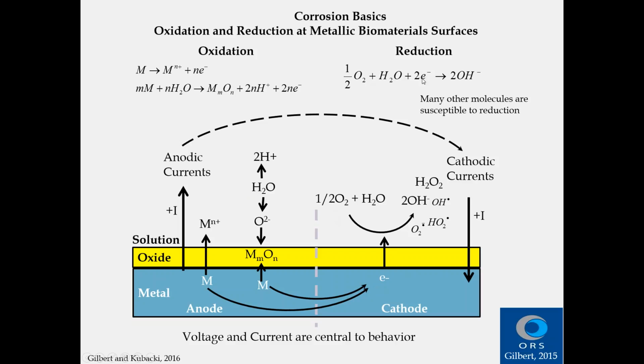Typically, we think of oxygen and water and electrons forming hydroxide ions, but it's also important to note that there are these reactive intermediates that can arise that include hydrogen peroxide, hydroxide radicals, hydroperoxyl radicals, and superoxide anion. All of these show up in small quantities as a byproduct of this reduction reaction, and these, it turns out, can have some very profound effects. Indeed, they are very similar to molecules generated by the inflammatory system to fight infection. And so the consequence of these molecules on the biological system will be discussed in a little while.